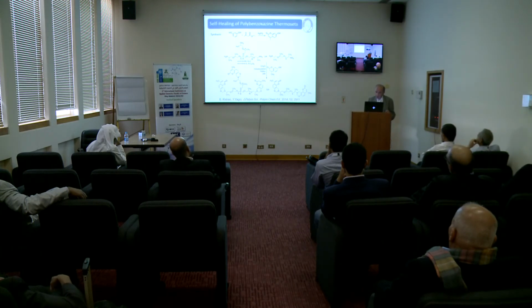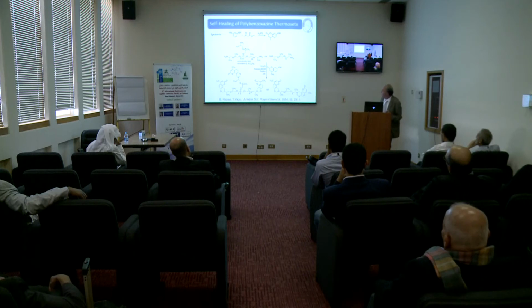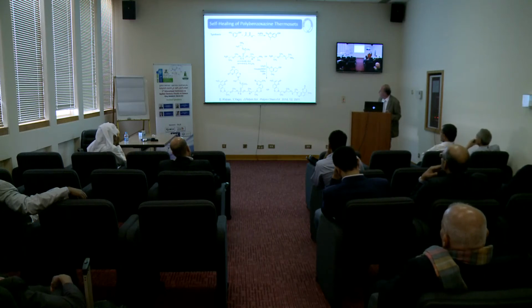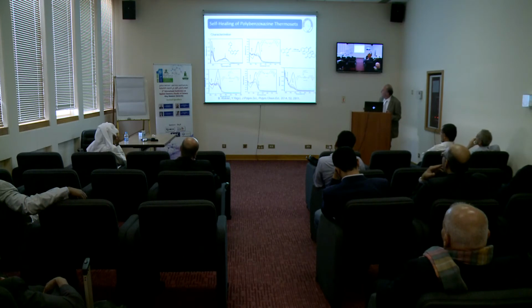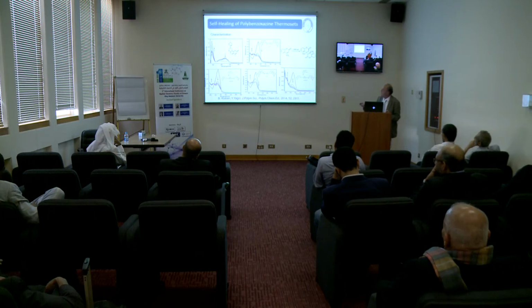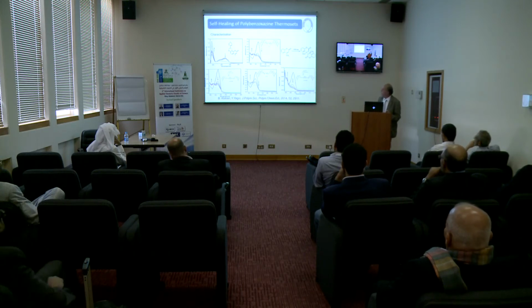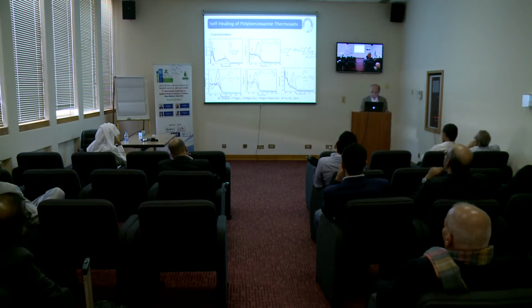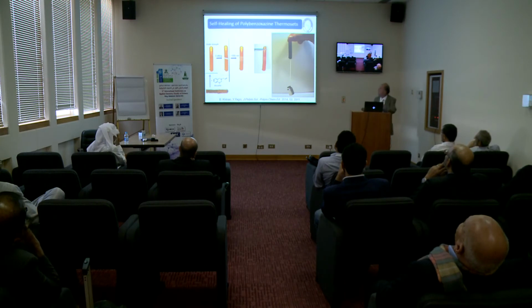So this is another strategy we measured. Maybe I should go further there by again polypropylene oxide here and benzoxazine units attached here and some kind of coumarin group is there. This shows the chemistry there. As you see, we can follow the dimerization by UV absorption spectra. The coumarin moiety by irradiation, it goes down and there is new absorption developing. Once you form the dimer, you can also adjust the going back system there. Again, it shows the photodimerization process.